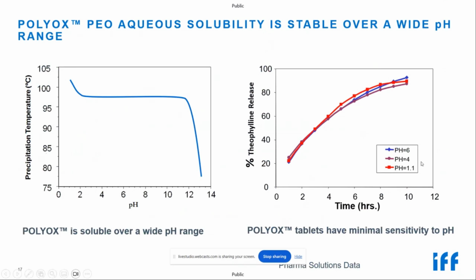The right graph shows a model matrix formulation using theophylline and Polyox PEO. The tablets were put into 3 different pH mediums ranging from 1.1 to 6. The dissolution profiles are almost identical, showing that the release from PEO tablets is pH independent as long as the API solubility is pH independent as well, or not sensitive to pH changes.